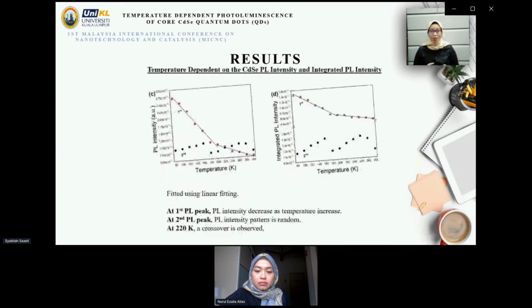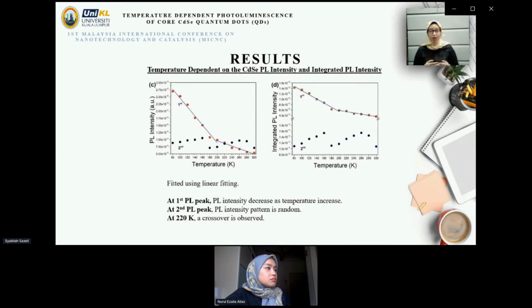Next, the result for temperature dependence on cadmium selenide quantum dots PL intensity and integrated PL intensity. A simple linear fitting is used for further analysis for both. However, both fittings can only be recorded for the first PL peak compared to the second PL peak. For the figure of PL intensity versus temperature, at the first peak, PL intensity decreased as temperature increased.